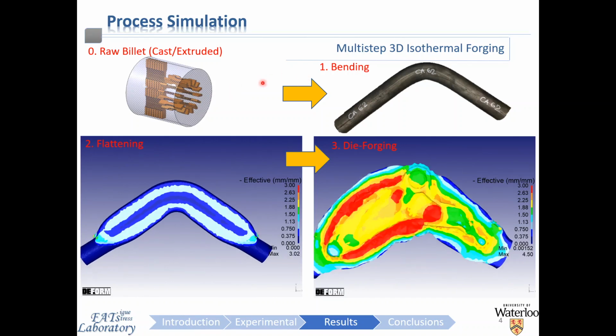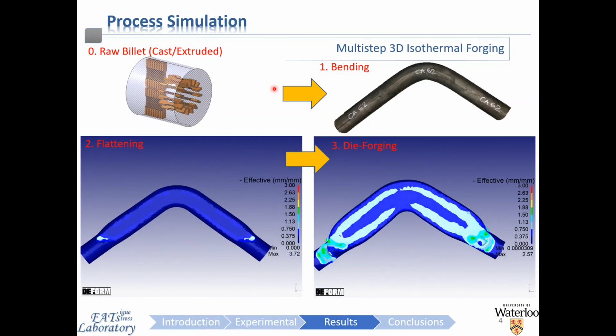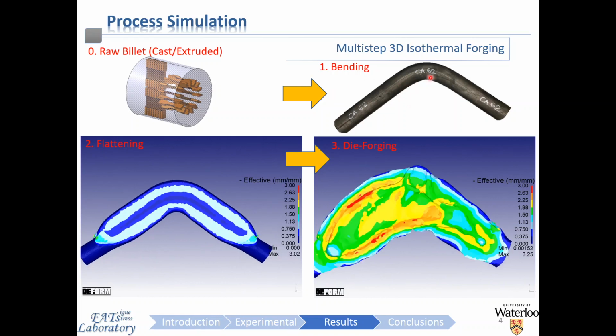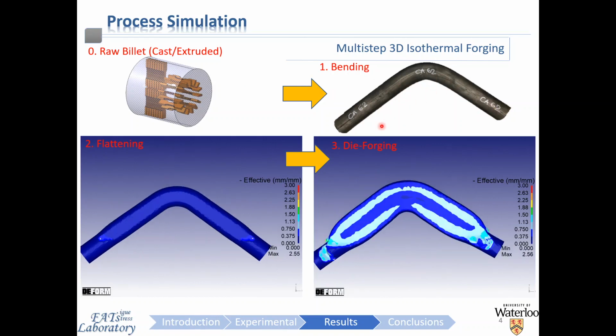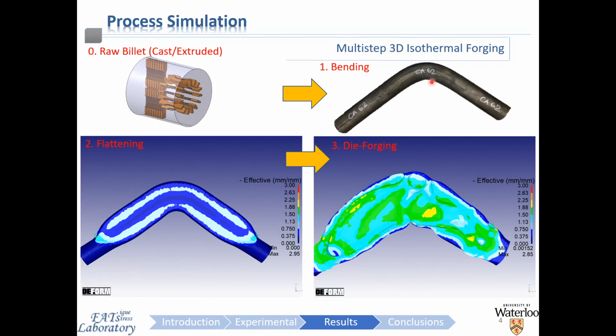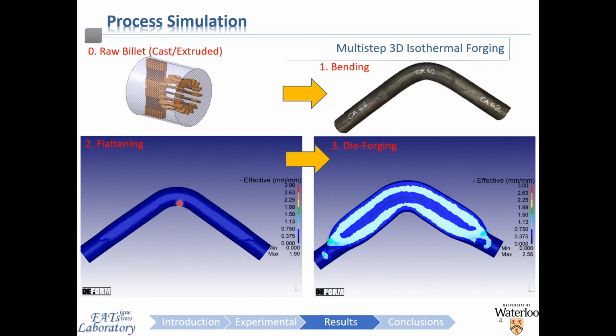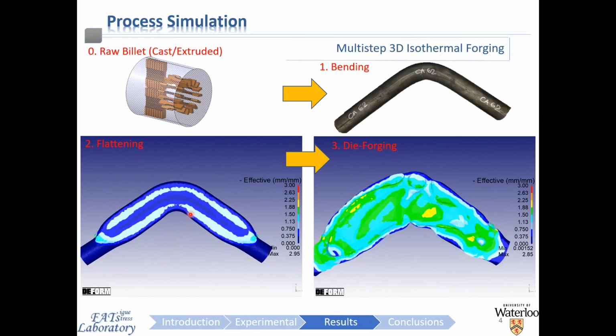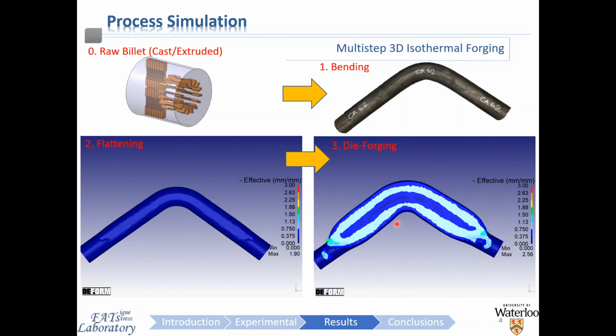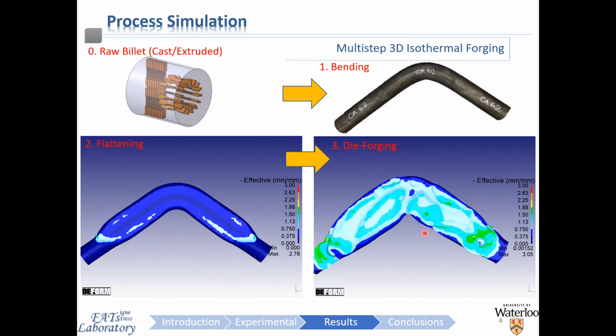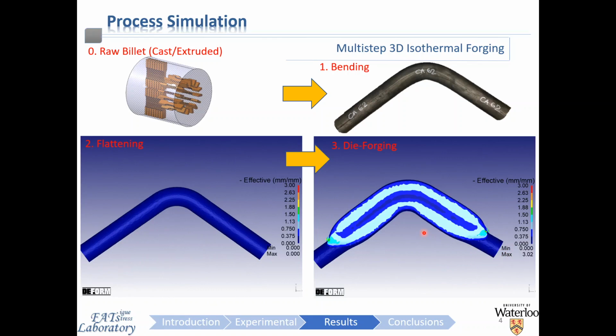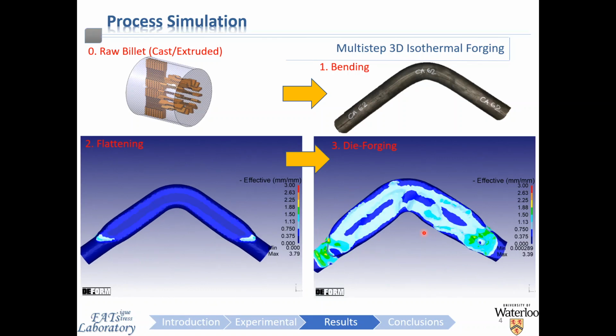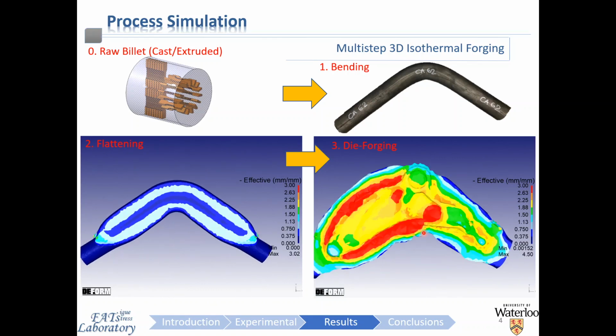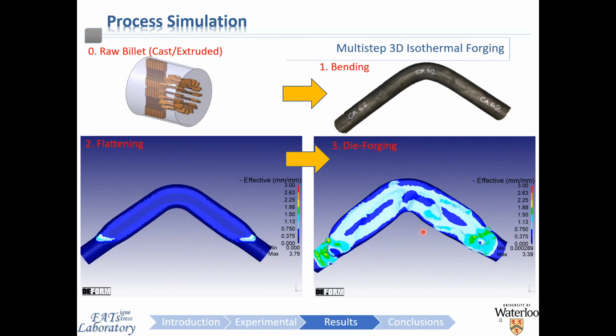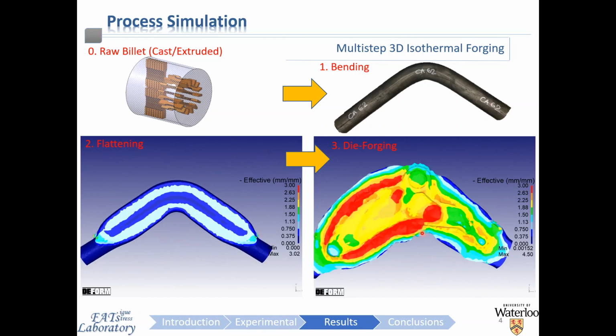We began each forging with a simplistic three-step process, incorporating the bending of the raw billet of the material into this boomerang shape of the component here, then followed by a flattening operation, which was used to redistribute the material to the necessary locations, and then a closed die forging, as shown on the right here, to achieve the near net shape component geometry. Depending on the temperature you choose to forge the component at, the strain history or microstructure memory may be retained or annihilated.